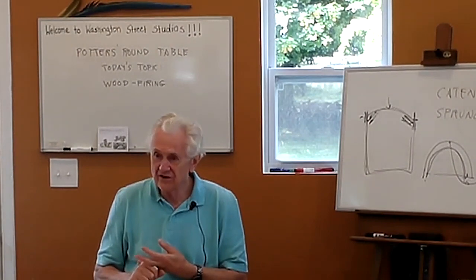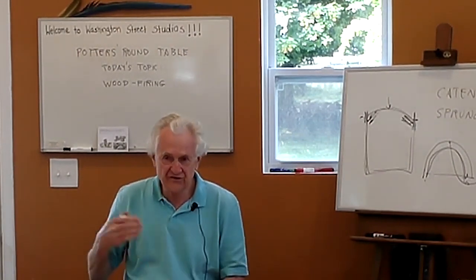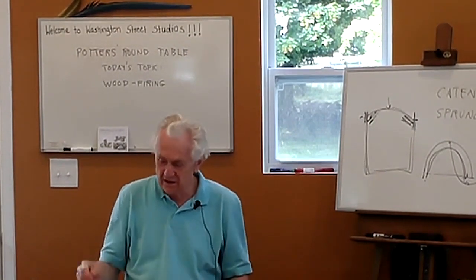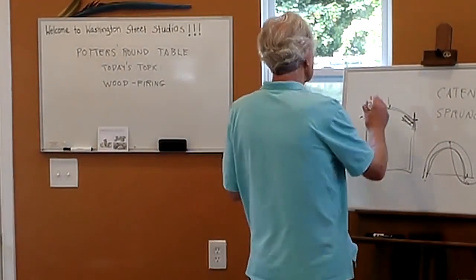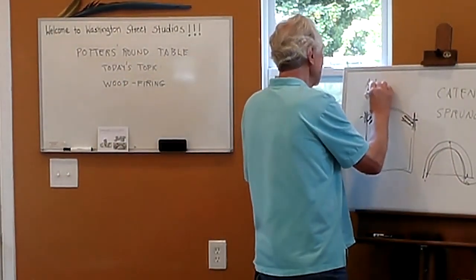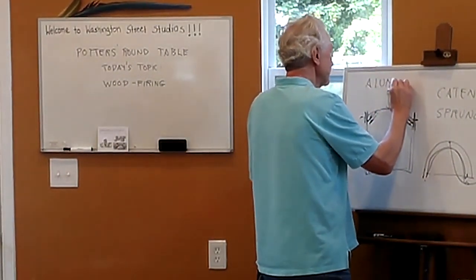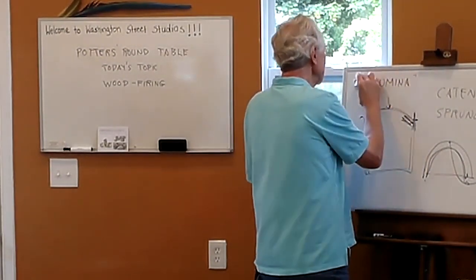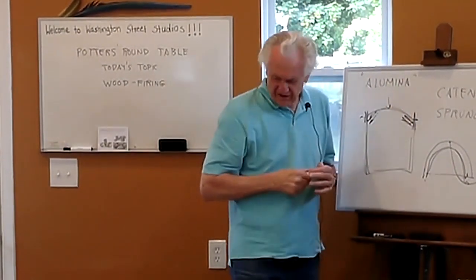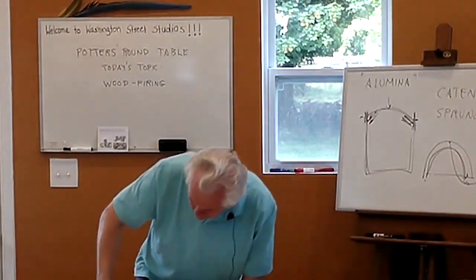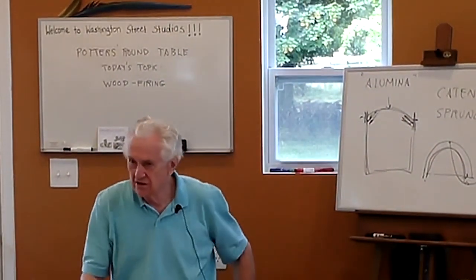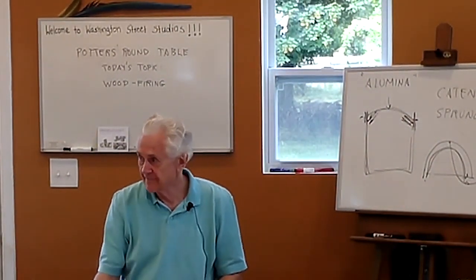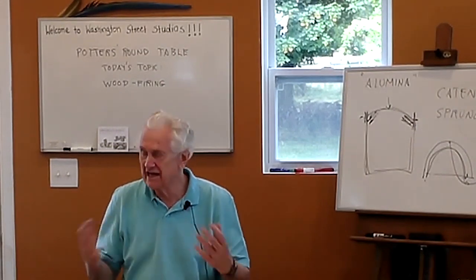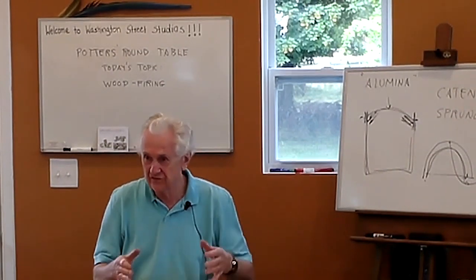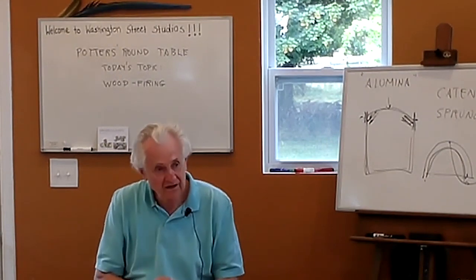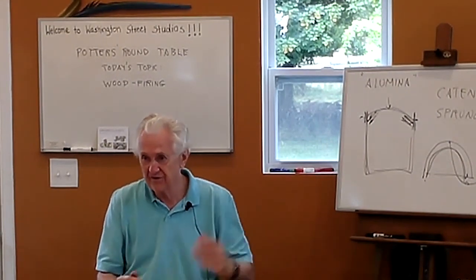Typically you want what are called high alumina bricks. Alumina is the nickname for aluminum oxide. If you get bricks that are high in aluminum oxide, they tend to resist the corrosion or the attack by the ash. So you can't just use any kind of bricks to build a wood kiln. You have to use a more specialized kind of brick to build the kiln. And at the same time, they're terrible insulation.